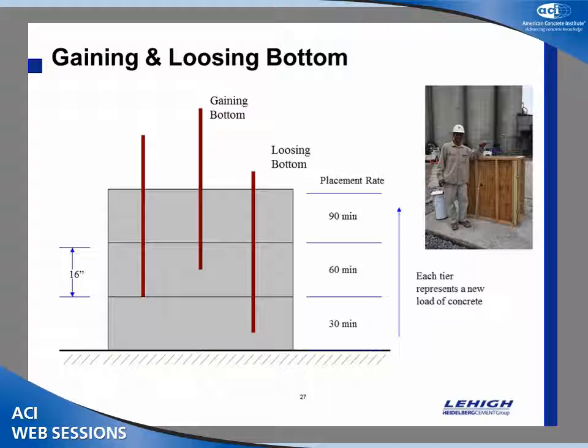So they have this terminology where they stick the rebar in, and if it goes down too far, that's called losing bottom. If it starts to rise up on you, that means you're gaining bottom. That means the concrete's stiffening, right? And then you have gaining bottom, losing bottom, and then you have kind of where you want to be. When they build the silo, this is a massive thing. You have to gauge that time. So you can't go too fast, and it can't go too slow.